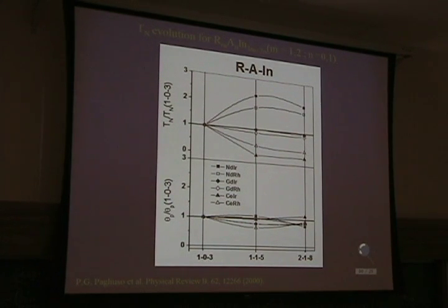So if you are really tuning the density of states, for example, between these compounds, right? And say, well, we are tuning somehow the number of carriers or your Fermi level. You are really changing the RKKY interaction. Then you should see a change for gadolinium too. It's a pure spin system.